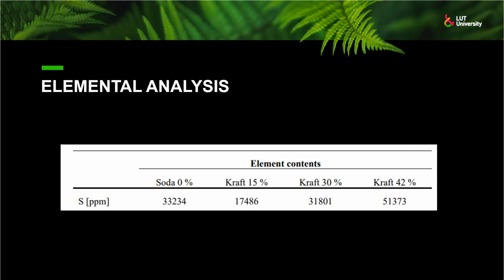Approximately the same volume of sulfuric acid was added in the preparation of acidic cakes at all trial points, but soda lignin may have had more reactive sites available for sulfur in the re-slurry stage, which offers an explanation why the kraft lignin samples did not exhibit a similar sulfur intake.